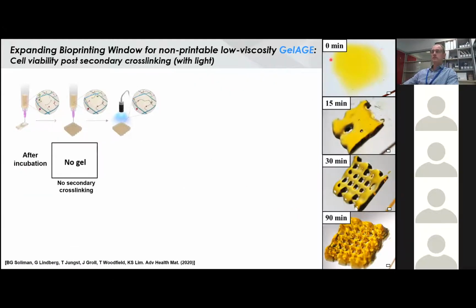So that then starts to mean that you can take something that's non-printable, and then over a period of time, it actually allows it to become printable. So again, if you essentially allow the redox reaction, of course, you won't generate a very stable long-term hydrogel, because you haven't necessarily done any secondary cross-linking.